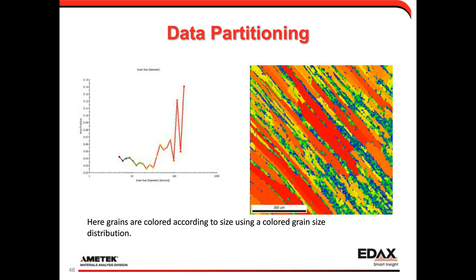So here what we've done is draw a grain size distribution on the left, and then applied interactively a color code across that grain size distribution. The small grains are blue, and then they go into the yellows and then up to the reds as the grain size gets larger. We can apply that color scale to the map to see the spatial distribution of the grain sizes on the image on the right. So we see the small blue grains, and the large, non-equiaxed, more elongated red grains bending from the top left down towards the bottom right.